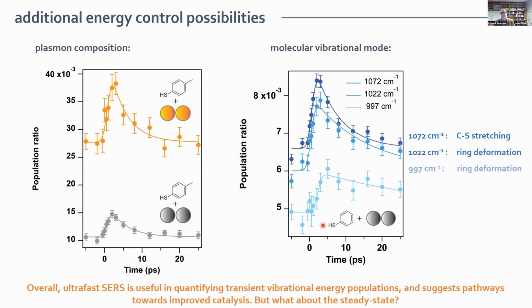That really is not a great way to think about it, and so we've shifted to talking about this population ratio. We see effects out to hundreds of picoseconds related to the acoustic phonon lifetimes of these plasmonic materials. And even in these steady state measurements, you see really out of equilibrium types of effects, even when you're averaging over long time periods. Thanks a lot.